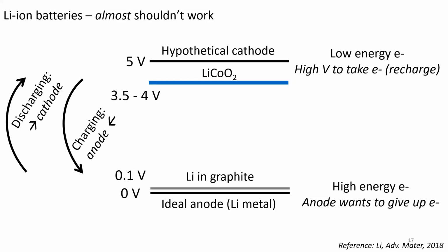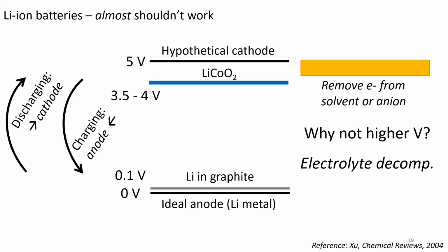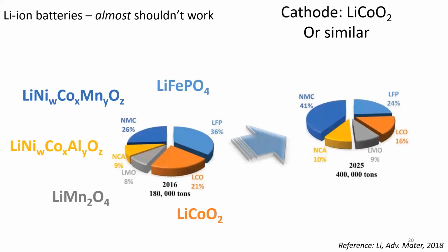I will tell you that there are cathode materials that would set up a 5-volt battery, but we don't use them. We don't use them because as you increase the voltage above 4 volts, which means you're lowering the energy of the electron in that material, we eventually start trying to pull electrons off of the solvent molecules or off of the anions that make up our electrolyte. And so using anything that creates a more powerful battery than about 4 volts causes electrolyte decomposition. So we can't use things beyond that.